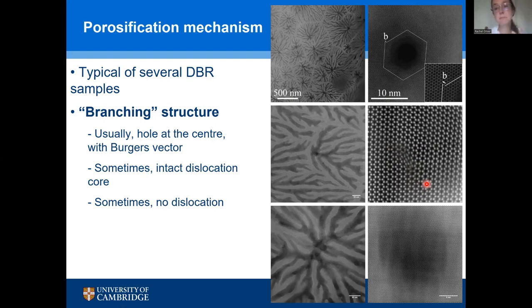At that point, because the bonding is not appropriate for the crystal, the bonds are weaker, which means the etchant can attack them. And we also think that any impurities tend to segregate to the region near that problem in the crystal, and that makes that region really susceptible to the etch. So there's no hole there to start with, but when the etch comes along, because the bonding's weak and because there's a little tiny bit of conductivity, it etches straight down that mistake of the crystal and